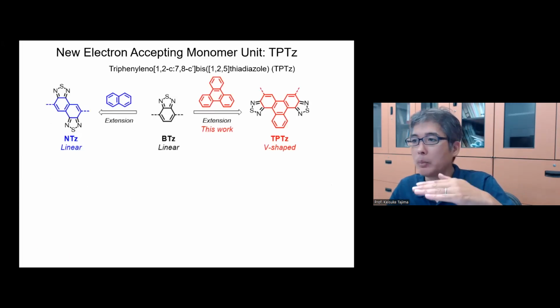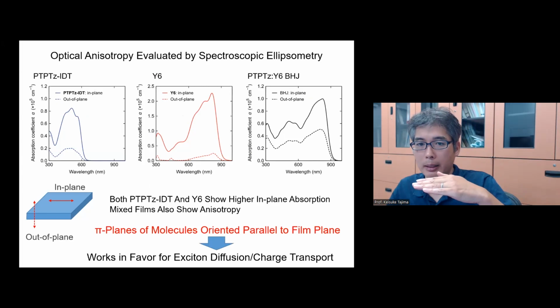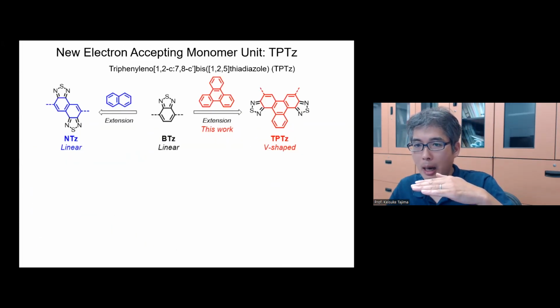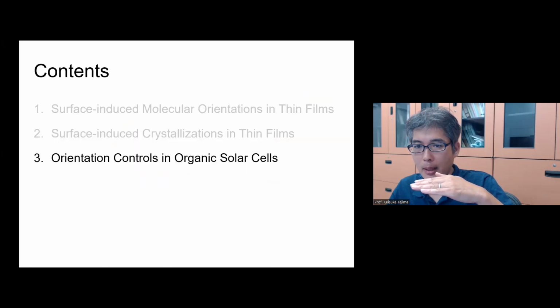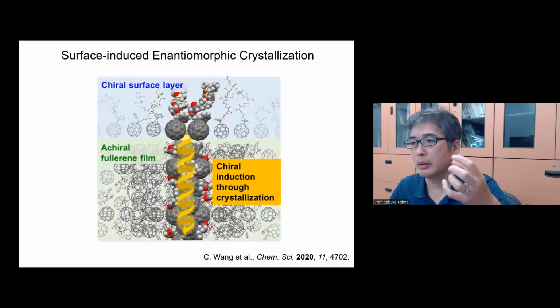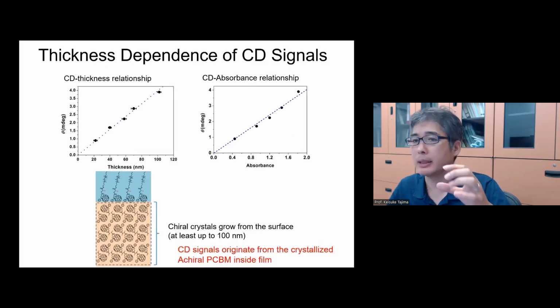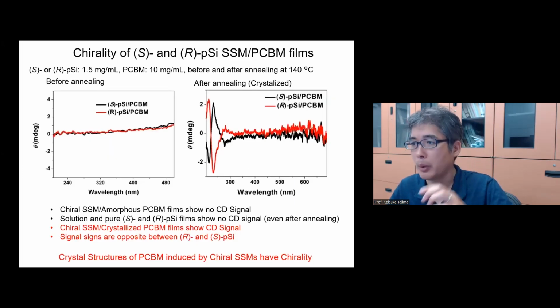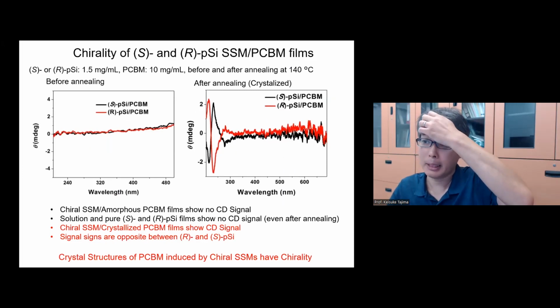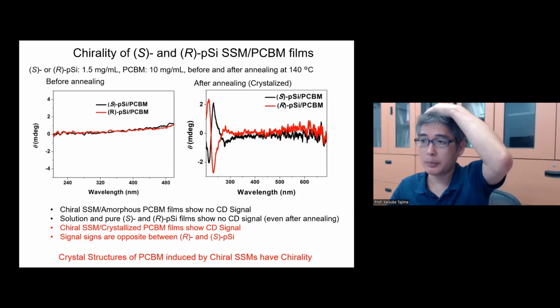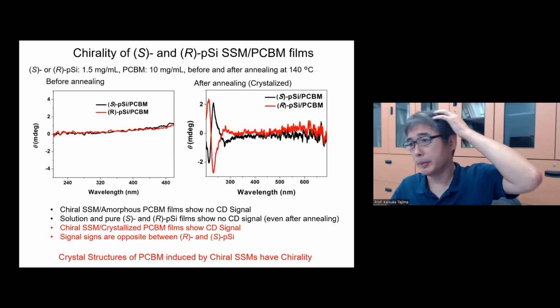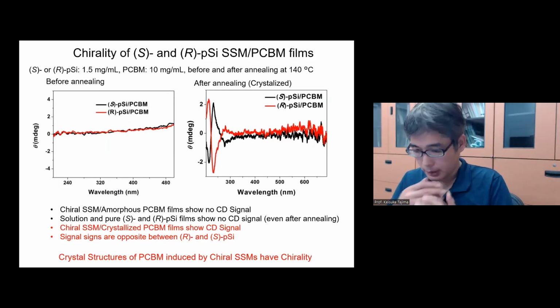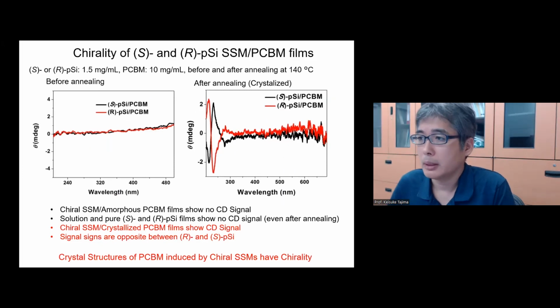And in the case of small molecules, it's like the fullerene case. Crystallization happens, and because small molecules move more easily than polymers, this change is really drastic compared to the polymer. So it really depends on the molecules. But I would say that polymers tend to have a small effect of annealing in terms of crystallization and orientation in thin film.